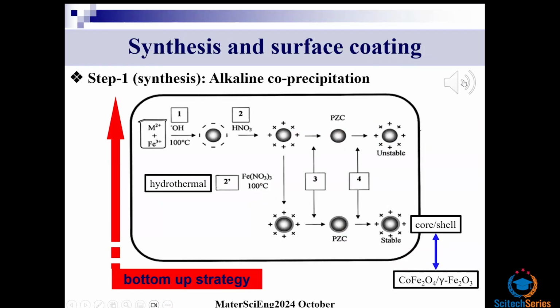In this slide, briefly, I will comment about the synthesis of magnetic nanoparticles, so cobalt ferrite nanoparticles. The synthesis is related to the alkaline co-precipitation of cobalt and iron salts in aqueous solution at very high pH. So it's alkaline co-precipitation at about 100 degrees centigrade. This co-precipitation produces the magnetic nanoparticles, and they are negatively charged. And then we can add some nitric acid and lower the pH in such a way that the surface of the nanoparticles is now positively charged. And at this point, we have two options.